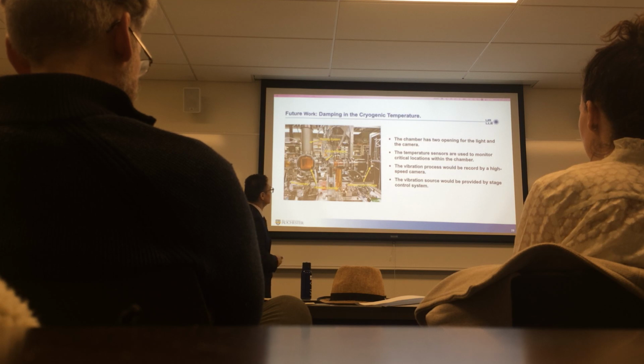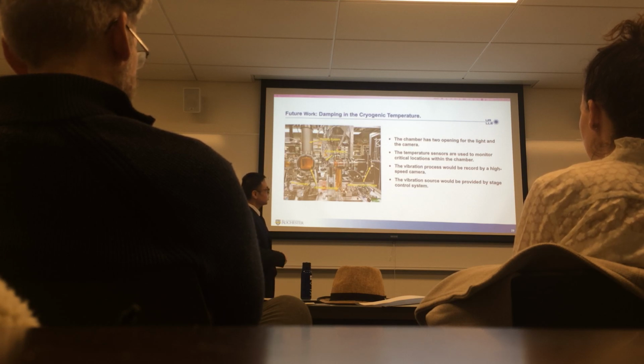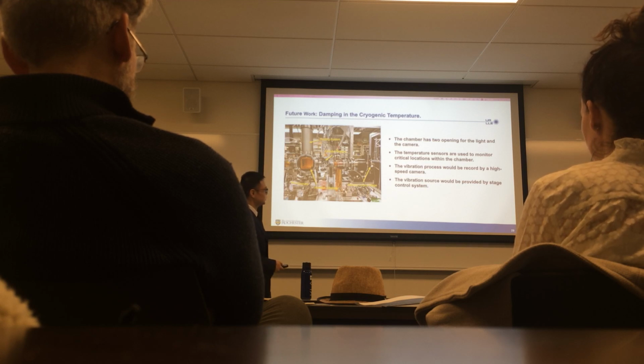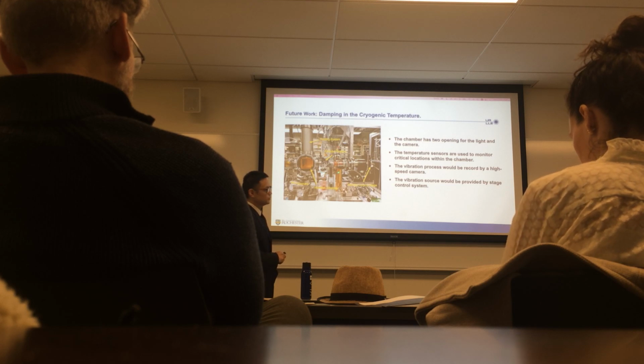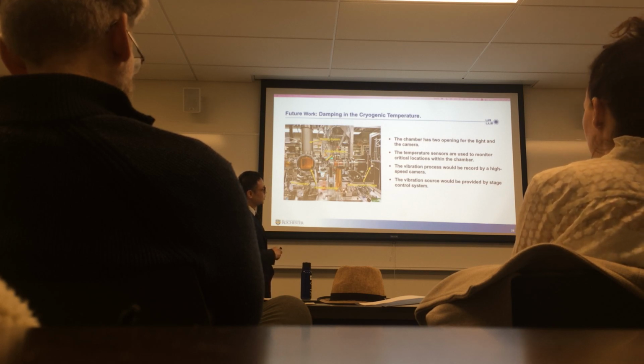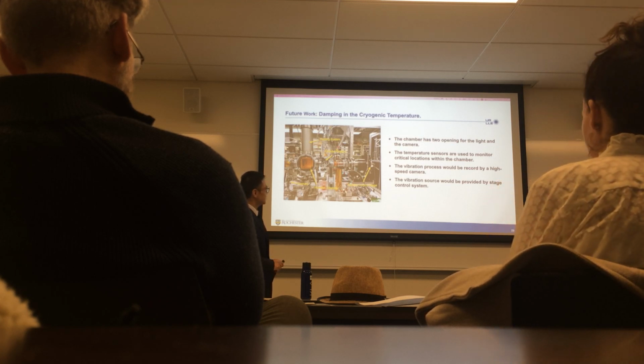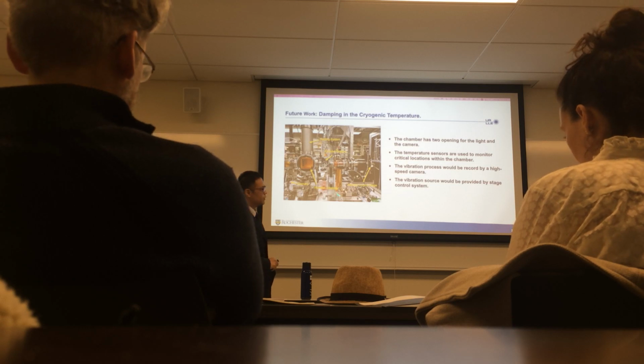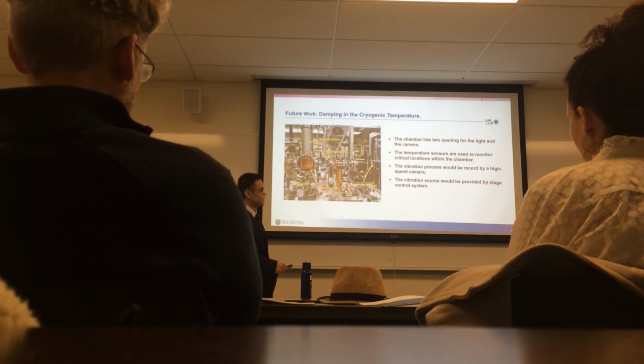Okay, for future work, we want to do the damping at cryogenic temperature. But there are two challenges for that. One is how we could create a cryogenic temperature for the target structures. Another is how we could record the vibration during the cryogenic temperatures. I figured out these systems can solve these problems because they have a cooling system. This cooling system uses helium and vacuum to create low pressure and a cryogenic temperature environment. We use a high-speed camera here to record the vibration process, and from the camera images we can get the damping displacement and time curve.